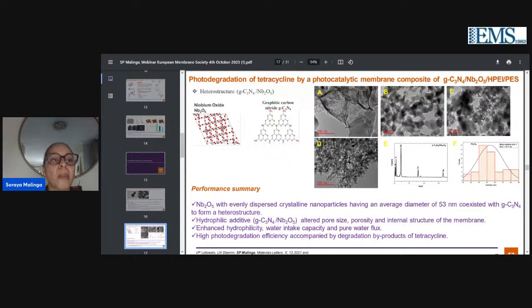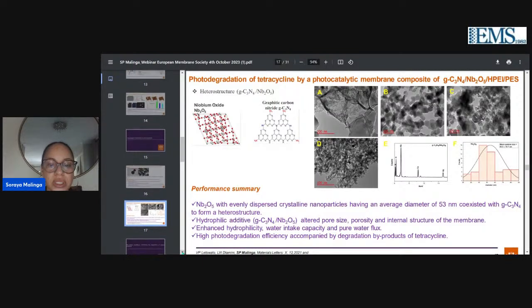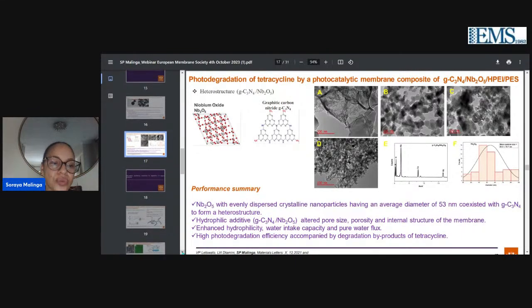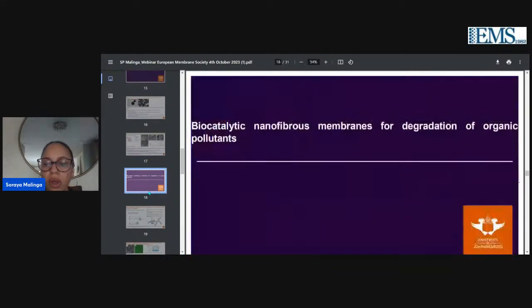But if you combine it with another photocatalytic material, it even gets more enhanced if you form a heterostructure. It is also hydrophilic on its own because it has NH2 groups. It is also antibacterial as well. So it was a good choice of support. We also found enhanced hydrophilicity, water intake capacity, and pure water flux, which was accompanied by enhanced photodegradation and byproducts of tetracycline.